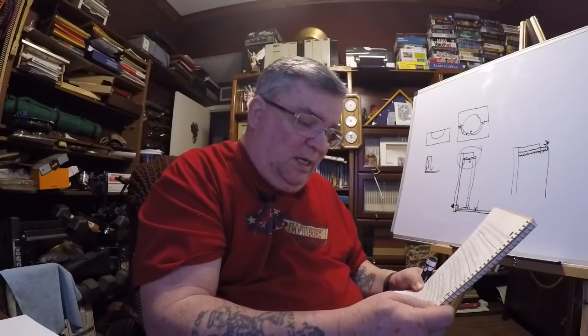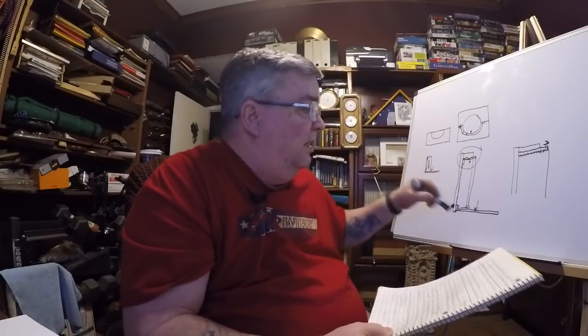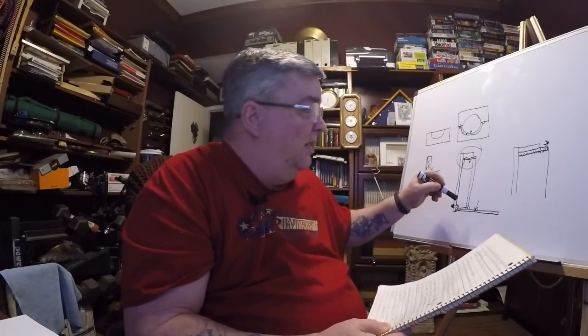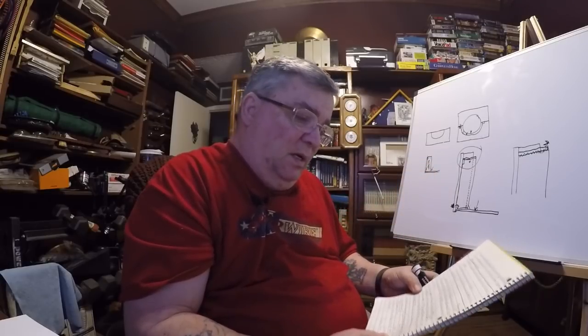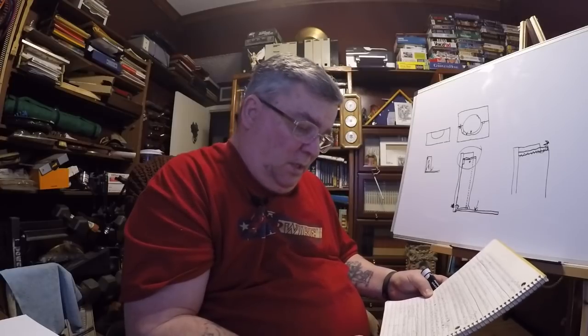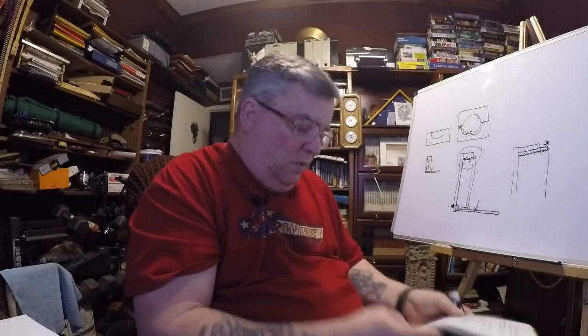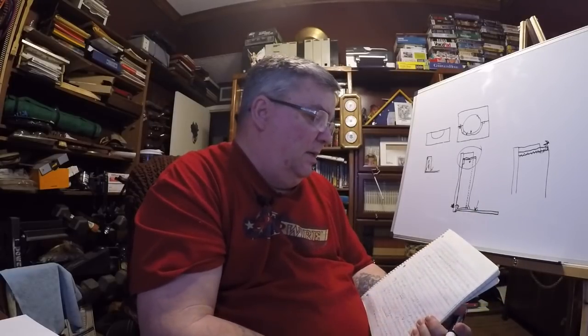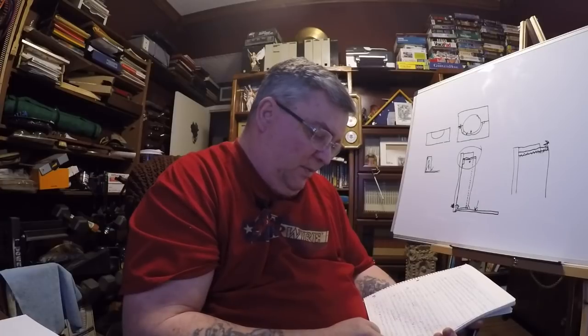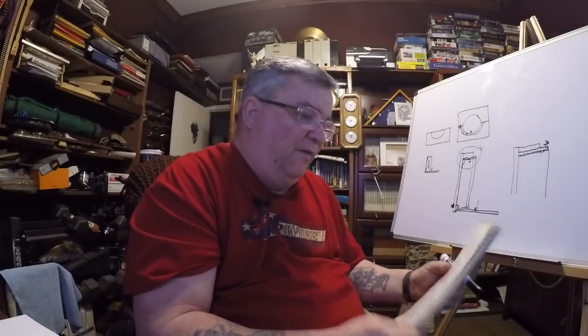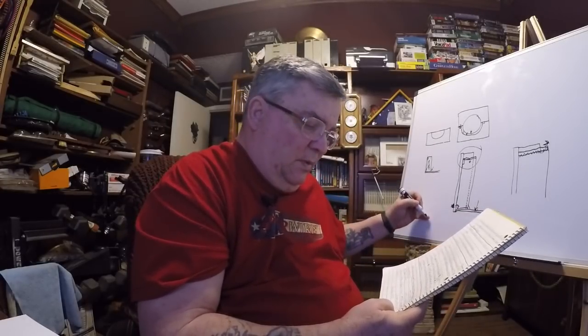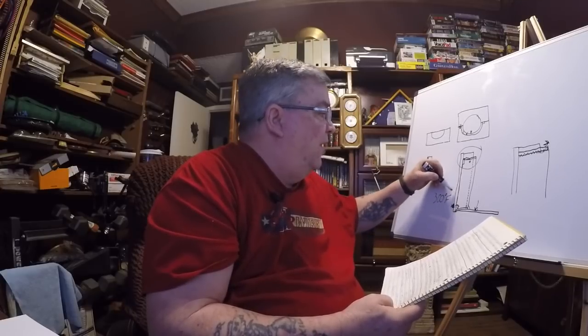And you're going to pour it into this. Now the mandrel is going to be heated up to 300 degrees. Where did I put it? Oh, wait a minute. I got pouring temperature for Babbitt is 795. All right. Tin. Did I write that down? Okay, the melting temperature of tin is 450 degrees. Now what you're going to do is bring this up, where did I put it, to 300 degrees Fahrenheit, so that this is ready.